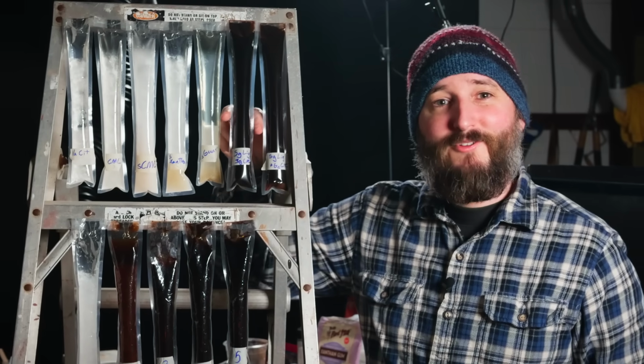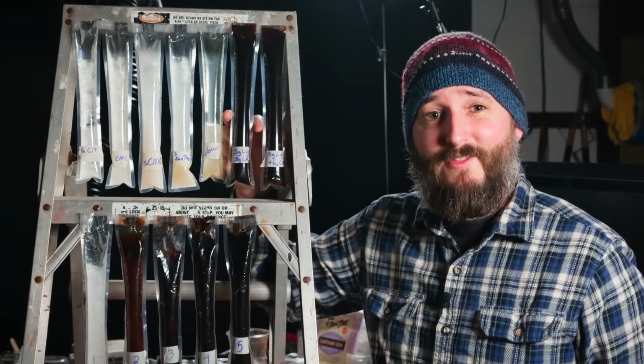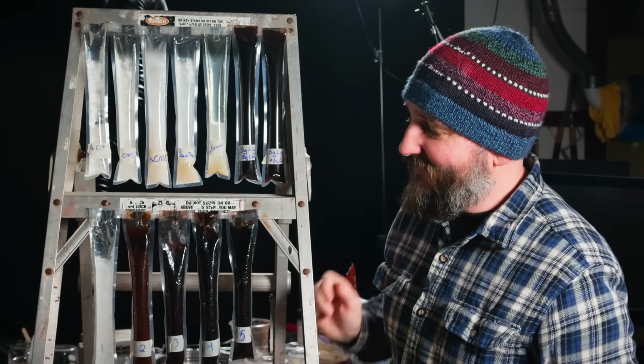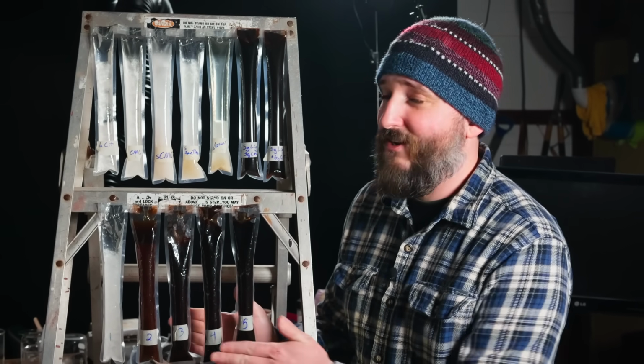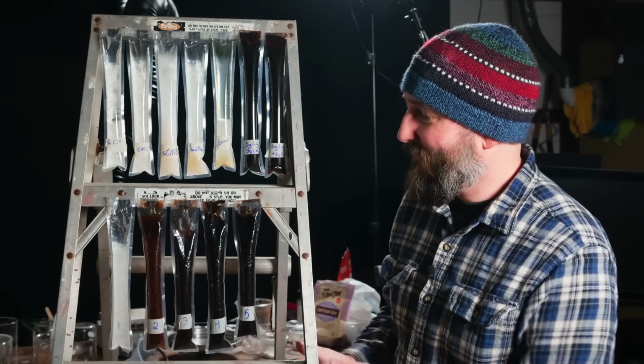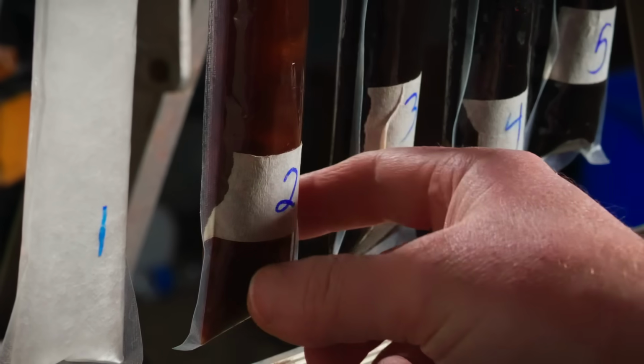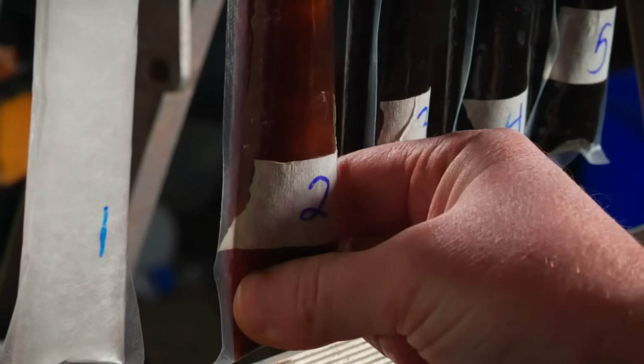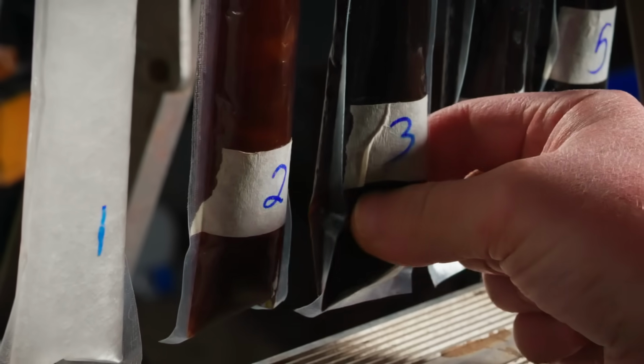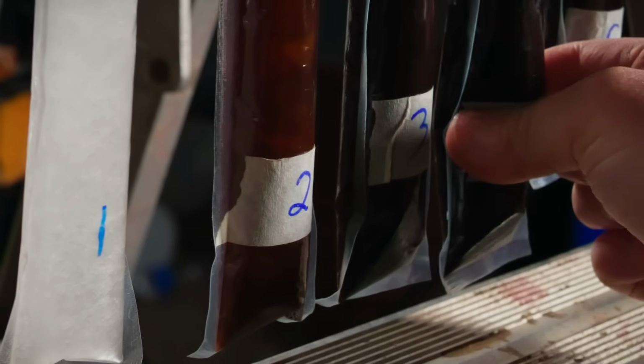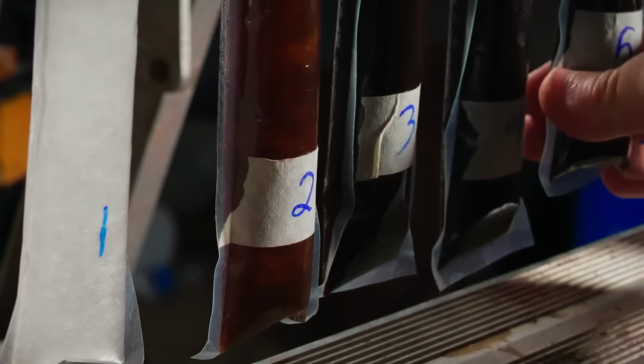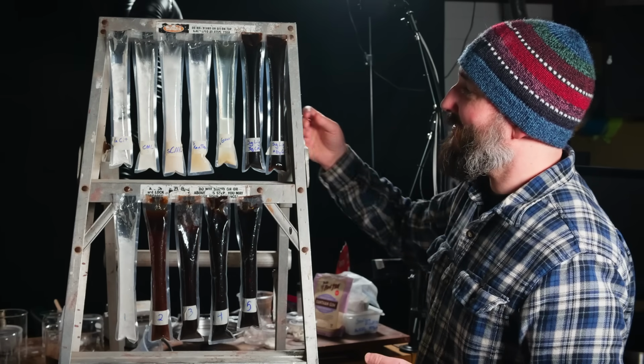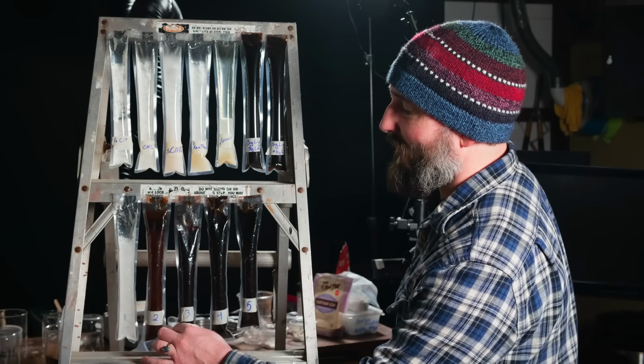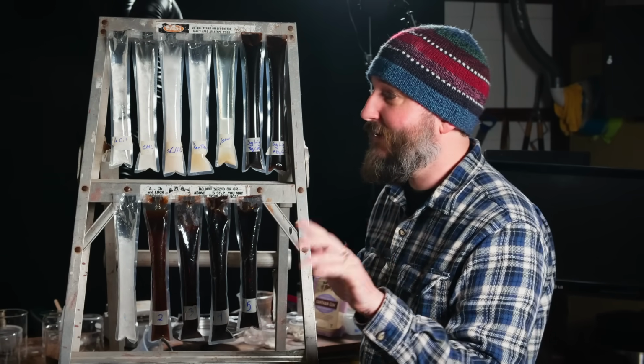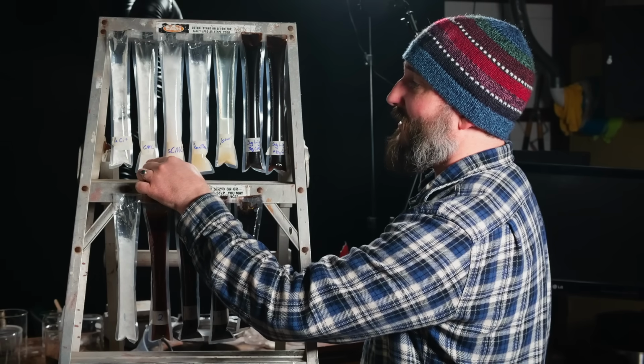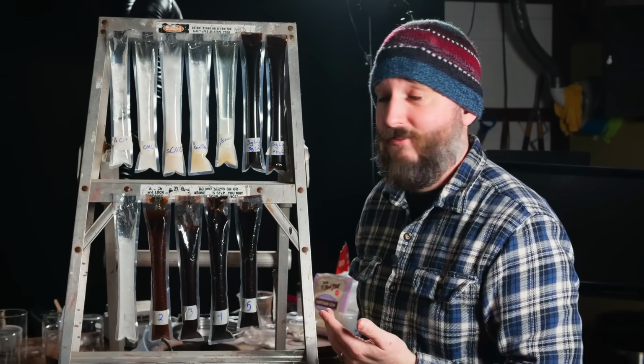Now these 2 samples are the ones that I'm most excited to try in the thermal cycling test, because as I saw that these lignosulfonate samples down here were not doing so well, and a lot of stuff was settling out of solution, I thought that perhaps this sort of detergent action, which I was leaning on for this lignosulfonate, just doesn't work on its own, and it might require a little bit of additional thickening. And so I decided to combine the number 3 test down here, that's 5 grams of lignosulfonate, with the CMC test up here using 3 grams of CMC.